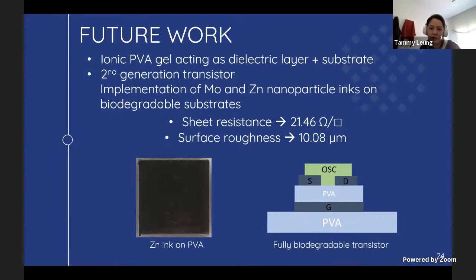Currently, we are finishing up the first generation transistor that was discussed previously, where we would like to develop an ionic PVA gel, which in this case can act as the dielectric layer and the substrate. Simultaneously, we are starting the development of the second generation transistor, which uses molybdenum and zinc biodegradable nanoparticle inks onto our biodegradable substrates. So far, these inks show a decent resistance. However, the surface roughness is extremely high compared to the previous inks that were discussed.